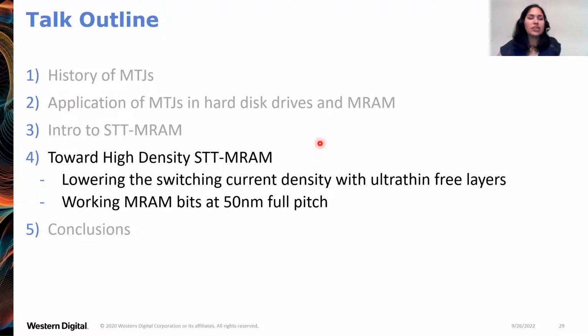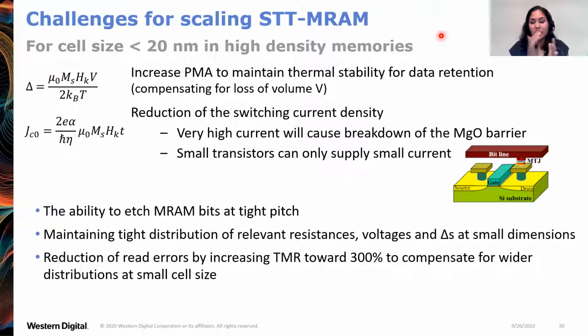And this brings me to what are the challenges for making a high density STT-MRAM. Okay. So I'm talking about MRAM cell sizes that are 20 nanometers and below. So these are much smaller bits than what's available now in MRAM products. And already when you're making smaller bits, you're losing volume, V here, V for volume. That means you're automatically going to have a lower thermal stability. So which means that you'll lose your data retention. So to compensate for that, we want to increase the perpendicular magnetic anisotropy, but we should do that, but still keep the switching current density low.